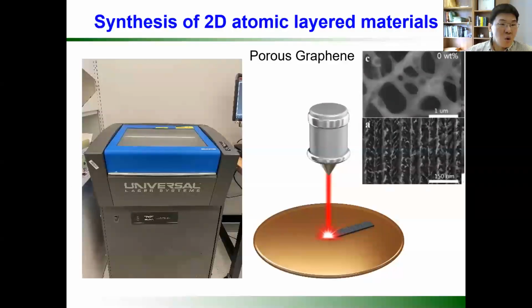Also in our lab, we synthesize those materials using different techniques. One of the techniques we can use to synthesize graphene is the laser. I mentioned the CVD technique, where with high temperatures of thousands of degrees, we can create hexagonally bonded carbon atoms. But CVD takes a long time to synthesize materials, up to 4 hours, though we can make it at large scale. Using the laser, we can synthesize graphene in a very short time scale, like less than a minute.